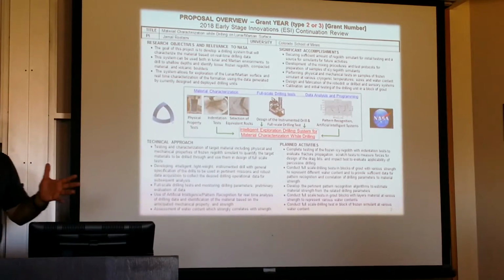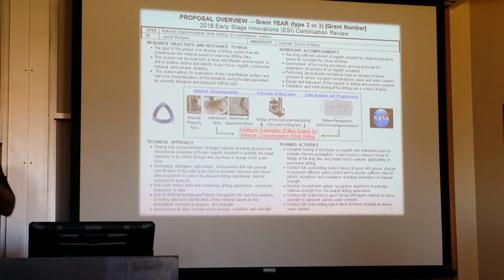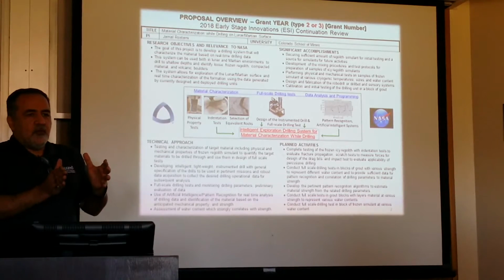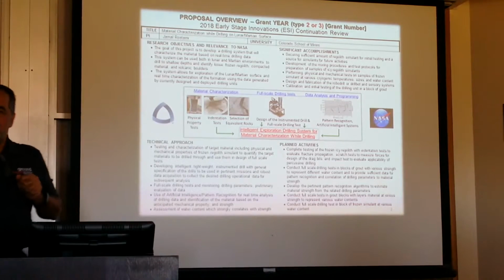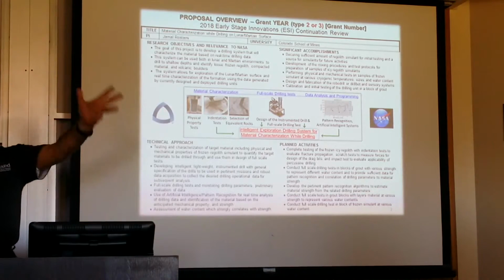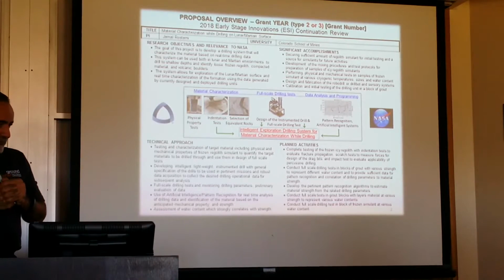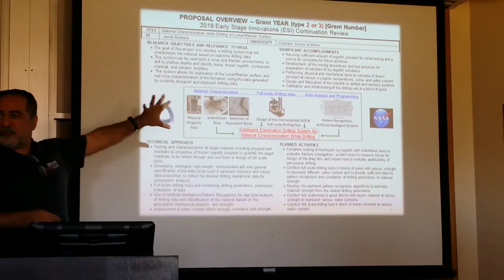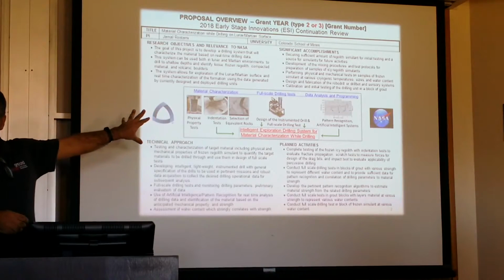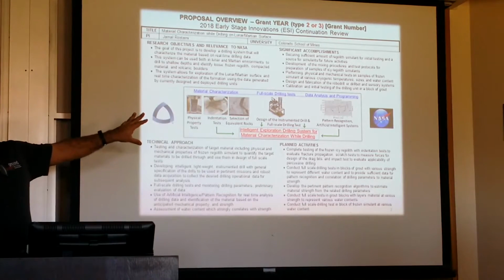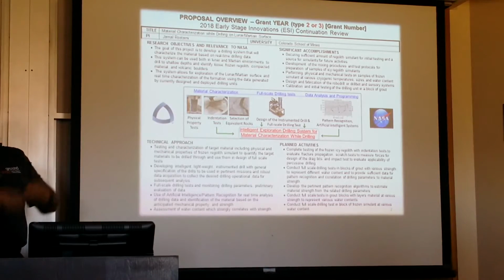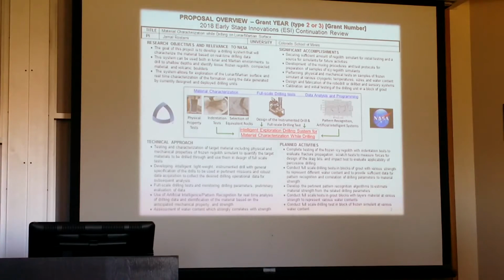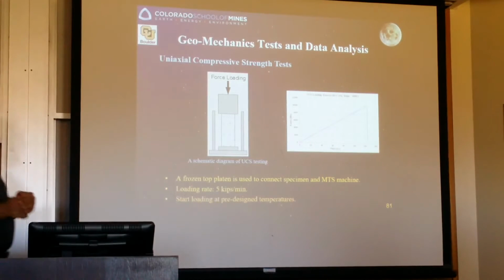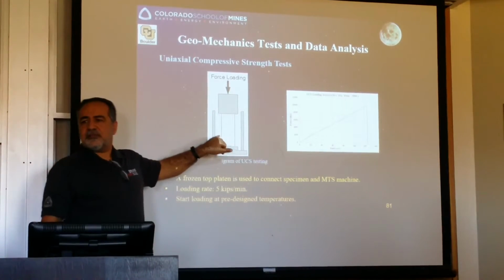And the theory was, and is, that the strength of the frozen regolith correlates with water content. So if I can measure a strength, voila, I can tell you what the water content is, right? In our previous project, we actually proved that drilling parameters can tell you what the strength is. So we are halfway there. Right now we are doing compressive strength testing, tensile strength testing, and everything.